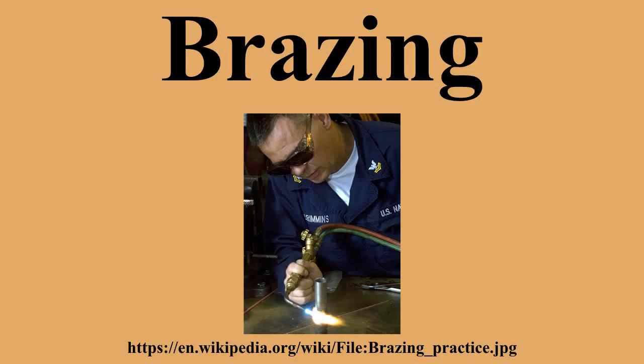Combusted fuel gas: 87% N2, 11 to 12% CO2, 0.5 to 1% CO, 0.5 to 1% H2. For silver, copper-phosphorus and copper-zinc filler metals. For brazing copper and brass.